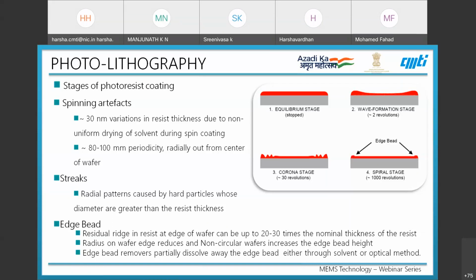The edge bead removers partially dissolve away the edge bead, either through solvent or optical method. So in order to take out the edge bead, we can use either a solvent method or an optical method to remove them from the wafer surface.